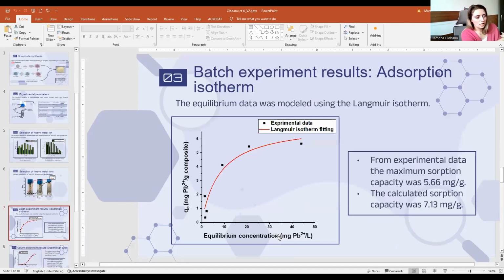So in the batch experiments results, we obtain almost 6 milligram per gram sorption capacity, and we fit it after that with the Langmuir isotherm, and this is almost a good fitting. Until now we obtain good results, but I will repeat it for the other good results, because this I put in my PhD thesis, and until now it is quite okay.